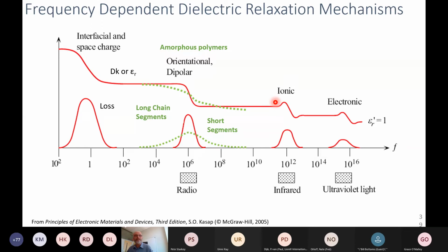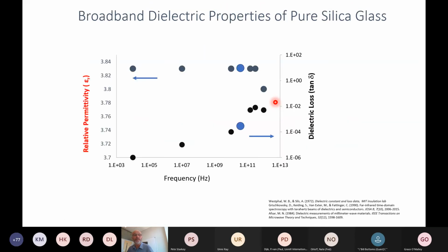and polymers. So let's look at an example of a ceramic material in this way where we're looking at fundamental polarization response. So here's the broadband dielectric properties of pure silica glass. So in this case, the permittivity shown here is around 3.8, and really doesn't change very much up until very high frequencies. And then here's the loss, or tan delta. And you can see here we're plotting a log scale. So as we sweep from the kilohertz range into the terahertz range, we're going up 4 orders of magnitude in the dielectric loss, where you can see here we're changing the relative permittivity actually very little.